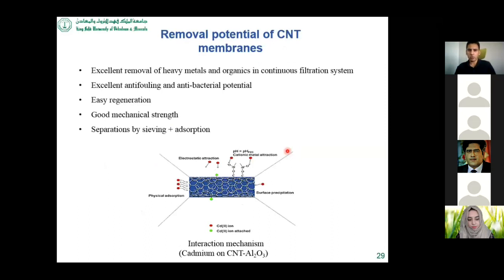Okay, I will not go in detail of what we did basically, but I will share that these membrane basically have the potential to remove the pollutant based on size, as well as there are some adsorptive characteristics. So the molecule can be attached to the surface. So this is a unique feature for this membrane. For example, if the surface is negatively charged, which was in our cases, so the cations, for example, cadmium are attached to the surface due to electrostatic interaction. And similarly, there are various sites where molecule are adsorbed on the surface. Some physical adsorption will also occur. So the attractive feature in this membrane is the molecule can be separated based on size, as well as it will be attached to the surface where they can be removed from the water.